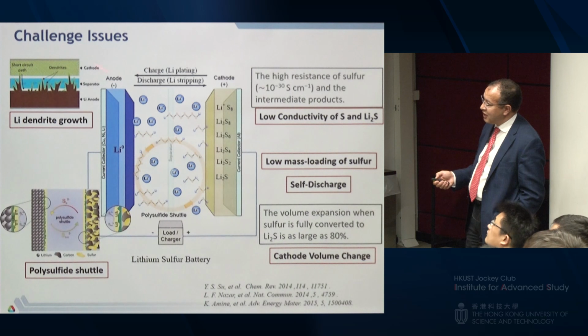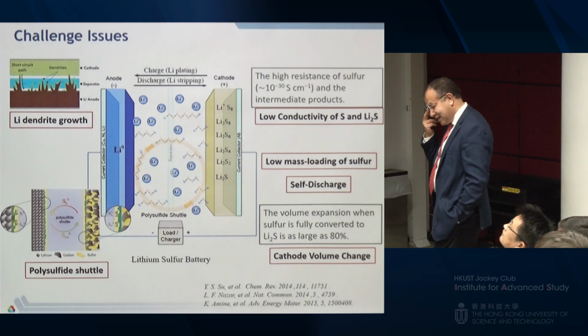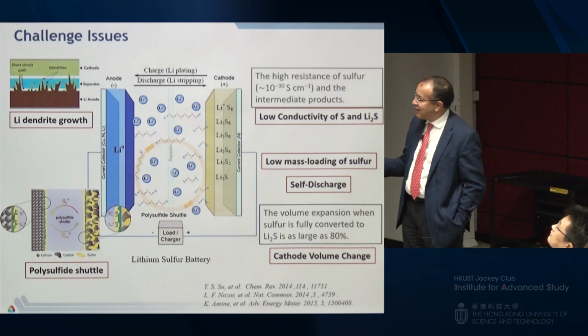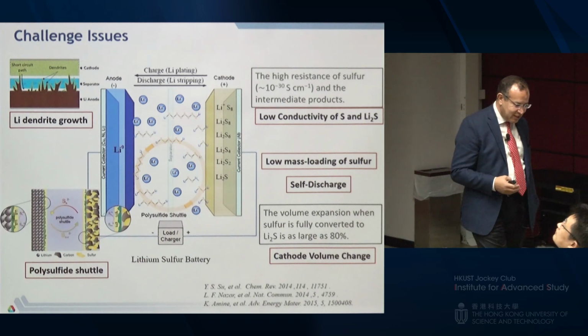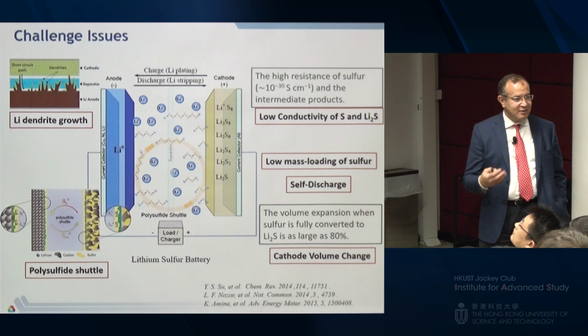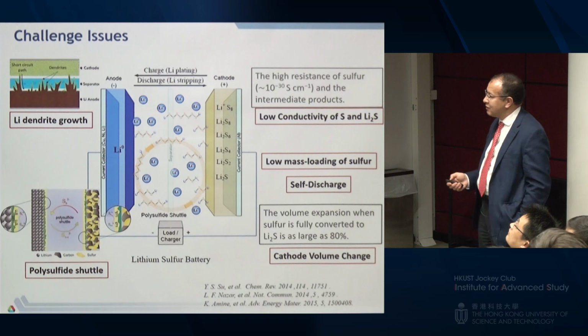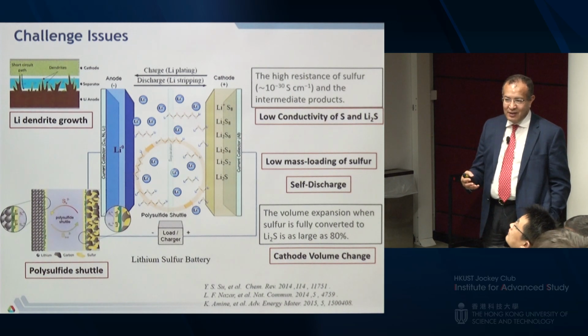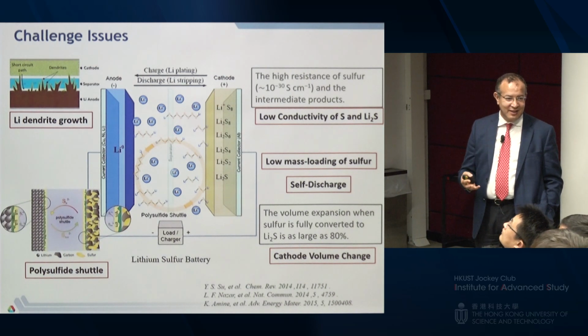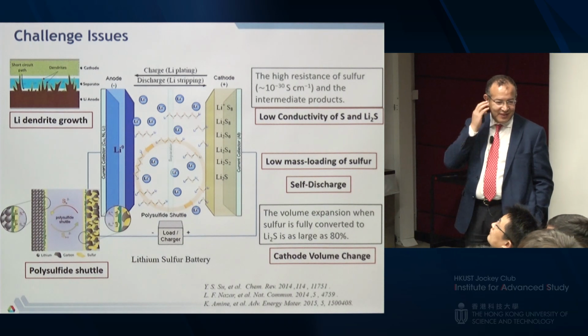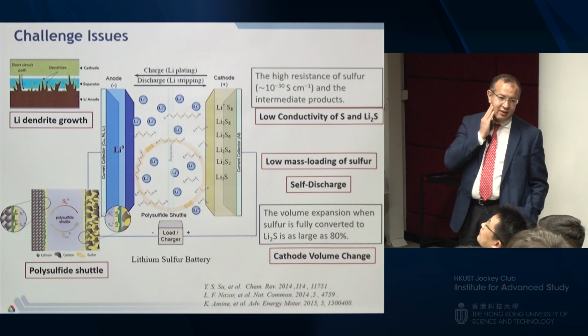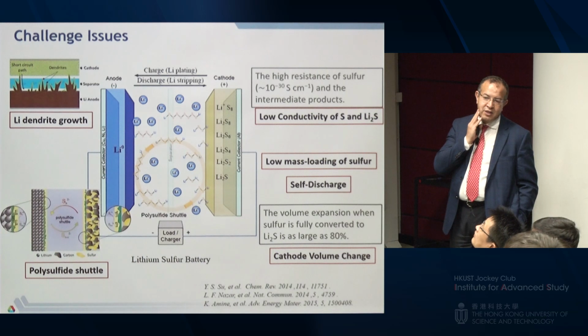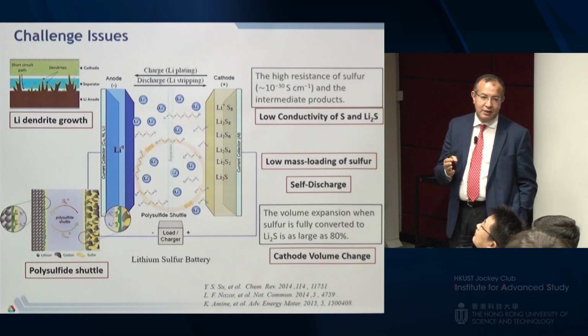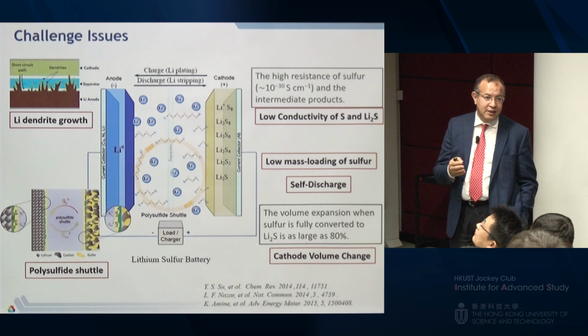You can see these are the challenges. One of the problems is sulfur is insulating. It's 10 to the minus 30. So you really have to put a lot of carbon to create some conductivity at the electrode level. So if you do that, you're going to use a lot of inactive material, and that can drop the capacity. Some people use 50%. So you have to maximize the active material in your electrode to get the energy you need.